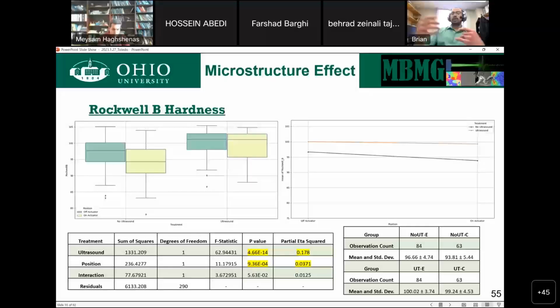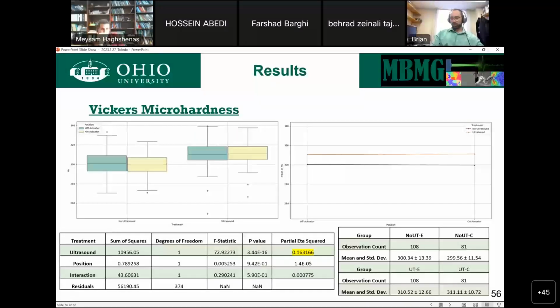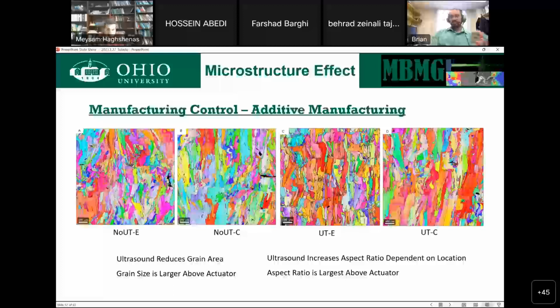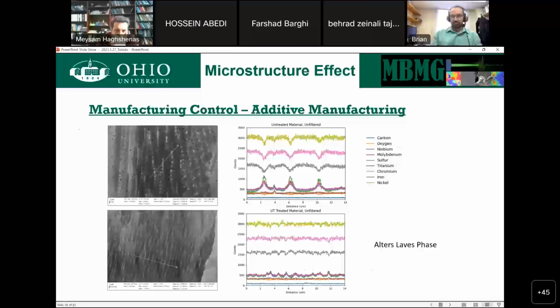So this was tested both on and off the transducer. So I showed you we did studies where samples were directly above the transducer and studies where they were off on the side. Both showed an increase in hardness, but those that were on the actuator showed a better increase in hardness. And we saw that across both global scale hardness, or a Rockwell scale, and across micro hardness. But looking at these images, very, very little difference in the actual grain structure itself. It all ties down to this, which is the spacing of mostly your Laves phase, but your sub grain structure that you see going on here, they're a lot more evenly dispersed, a lot less variability across the sample.